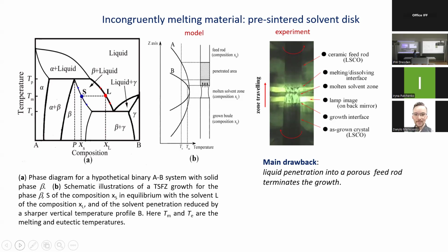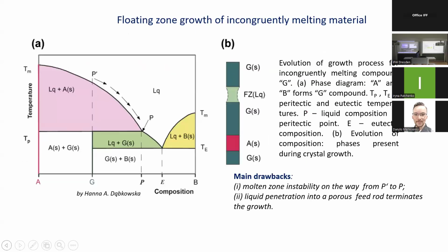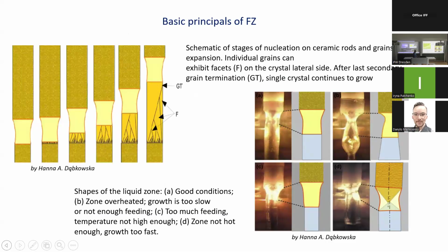And here is how it is done in a real growth experiment of the LSCO high-Tc material. You see the ceramic feed rod, the growing crystal, the lamp image, and the molten zone. It was obtained by melting a solvent disc. And more important, this part is the so-called penetration part. The liquid from the molten zone penetrates into the feed rod due to its porosity. And this effect is even more visible in this picture. You see this dark area is full of liquid, and a really porous feed rod sucks liquid from the molten zone and it terminates the growth. So you have no chance to grow your material if you prepare a low density feed rod.